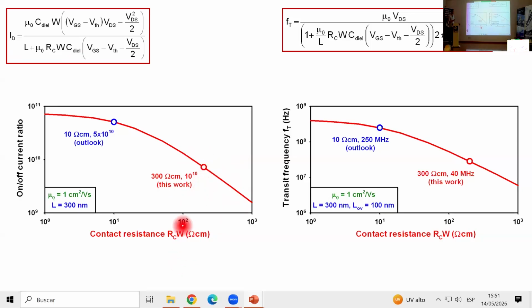So for a contact resistance of 300 ohm centimeter, we obtain an on-off current ratio of 10 orders of magnitude. Now let's assume that by making additional improvements to the materials that we use in the transistors, we're able to bring down the contact resistance by 1 order of magnitude, so something like 10 ohm centimeter. Then using this equation, we can expect an improvement by a factor of 5 in on-off current ratio. So this will be a huge further improvement. So there's a lot of incentive to further reduce the contact resistance of the TFTs.